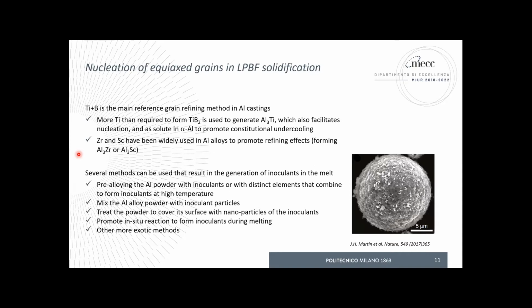Then, from a practical point of view, how can we induce such kind of nucleating effect? Oh, sorry. Before doing that, what kind of inoculants can be used? Again, it's not strictly necessary to invent anything new. From casting science, we know that titanium diboride is very common, very popular. Usually they do not use exactly the stoichiometric composition, TiB2. They use excess of titanium in the composition of the alloys, so that first we are able to form TiB2, but then additional titanium is used for generating the Al3Ti, and then even more titanium remains in solid solution to promote constitutional undercooling.